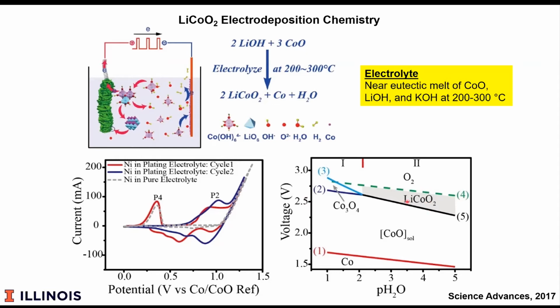So I won't go over the details of the Pourbaix diagram, but simply suffice to say that thermodynamically, there's a voltage and water activity level where lithium cobalt oxide will grow. If the voltage is too high, there's oxygen evolution. If the voltage is too low, one simply doesn't get oxidation to the appropriate oxidation state. And if the water activity is too low, the wrong phase forms. So, these diagrams are not too hard to construct from the thermodynamics, and then one has to go out and experimentally validate it in the laboratory.